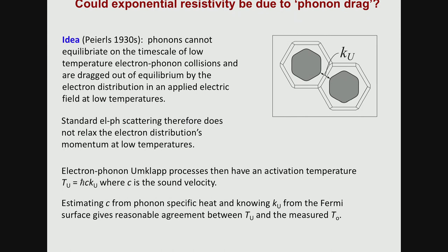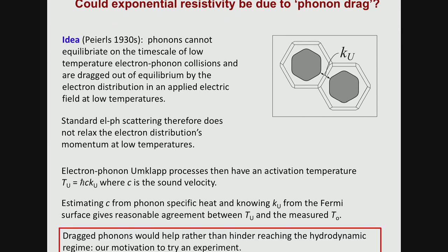So that, combined with the exponential onset, makes us wonder whether we're dragging our phonons, so that the normal electron-phonon processes involve phonon drag. And that's important because those dragged phonons are suddenly the friends of hydrodynamics. Normally, phonons are just the enemy of hydrodynamics, but dragged ones are the friends of hydrodynamics because that coupled electron-phonon soup conserves its own internal momentum. And that's exactly what you want for getting a combined viscosity from that soup. That's also something that had been considered theoretically in the 60s by Gurzhi. It's one of the regimes he wrote papers about.